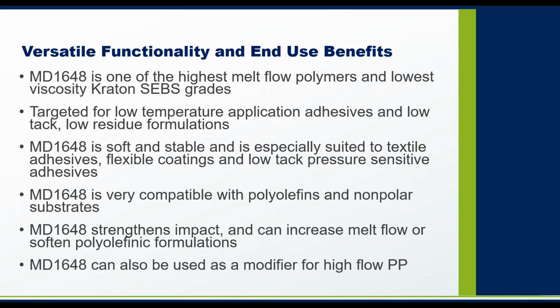To sum up, MD1648 is one of the highest melt flow polymers and lowest viscosity Kraton SEBS grades. The polymer is currently being used in solvent cast and coatings, melt extrusion, and injection molding processes. A broad range of adhesives can be made with MD1648, and the soft touch makes it an excellent candidate for textile adhesive, flexible coatings, low tack protective films, and elastic melt-blown non-woven fabrics.